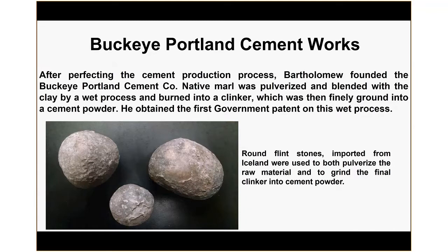And when we drive moisture off of calcium carbonate and the marl, again a source of silica, source of iron, we form a new set of minerals, and we form clinker, which are essentially pellets of various different sizes, gray pellets, which you then grind in a mill down to what we know as gray Portland cement, which is in a powdered form.